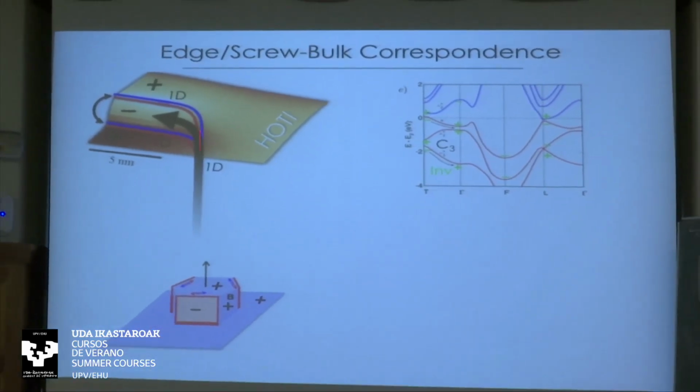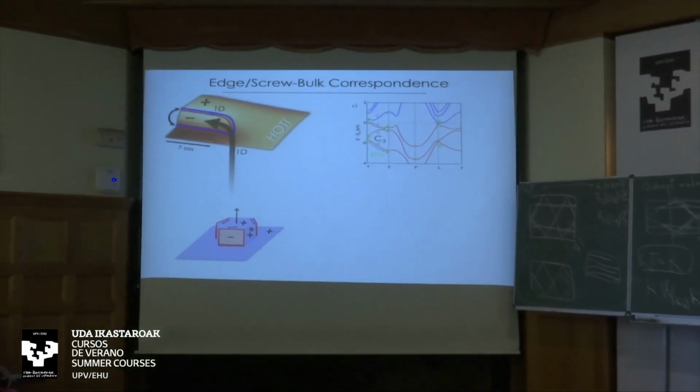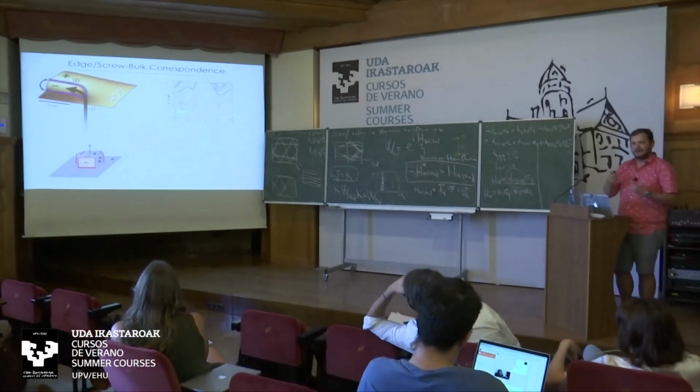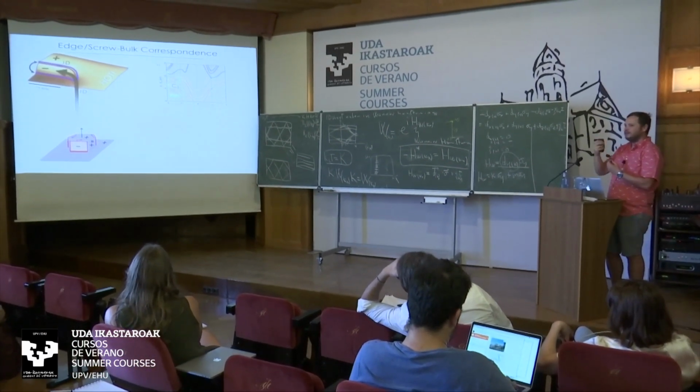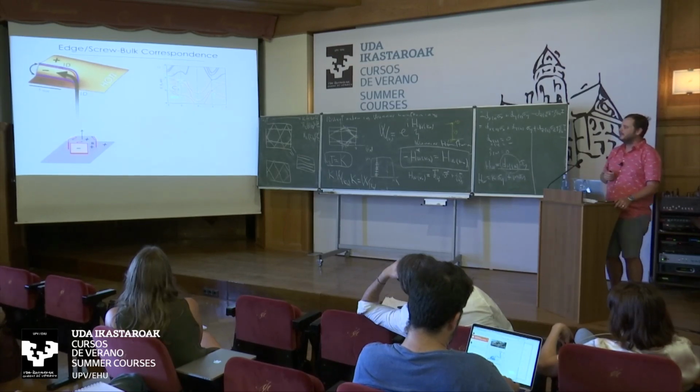So the screw dislocation, again, kind of collects this side facet into a one-dimensional object, which means that here they must hybridize. They really sit one on top of the other in real space, and we would expect to see a very clear scattering from one helical mode to the other, and their quasi-particle interference gapping towards the screw, which we don't really see in our measurements.